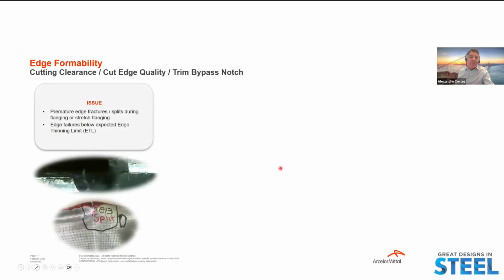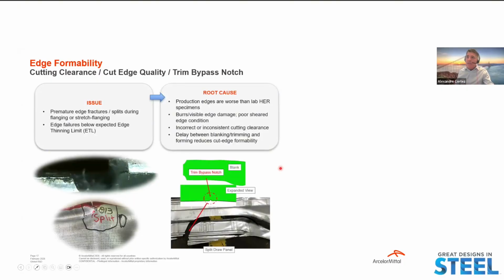Another edge formability concern is the cutting clearance and the cut edge quality, and trim bypass notch. The issue is premature edge fracture, splits during flanging or stretch flanging. Edge failures occur below the expected ETL. As a root cause, production edges are worse than lab HER specimens: visible burr and edge damage, poor shear edge condition, incorrect or inconsistent cutting clearance, and delay between blanking, trimming, and forming reduce the cut edge formability.